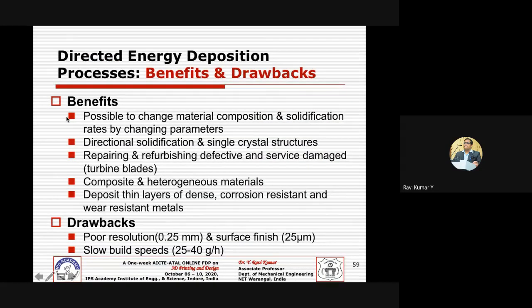To talk about the benefits and the drawbacks, you have the possibility of changing the material composition and the solidification rates by changing the parameters. That's quite interesting if you compare with traditional welding or any traditional joining. Here you get directional solidification and single crystal structures. It's quite amazing to control your grains and grain sizes and columnar grains, right? So it's quite interesting once you have this kind of technology.